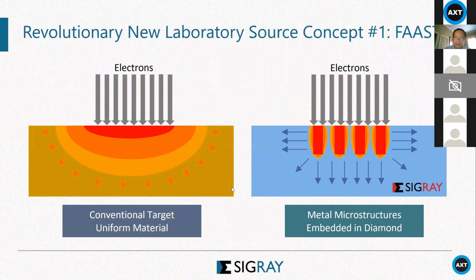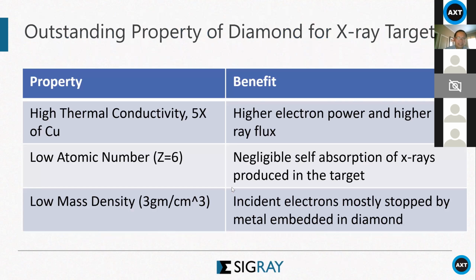So our target is unique. We have a diamond substrate and put metal inside the diamond. By doing that, we have a far better thermal conductivity for the target. And also by microstructuring the target, we have a larger thermal gradient. As a consequence, we have a much better thermal dissipation property. We can have more electrons bombarding the target and produce more X-rays. So this slide just illustrates that diamond is a far superior material to use as part of the target.